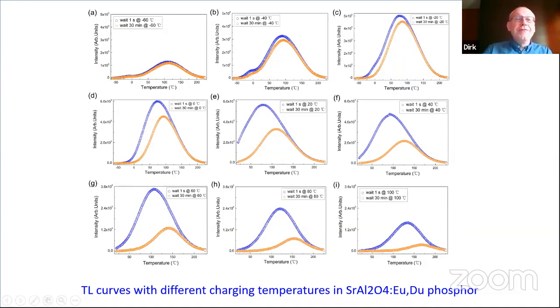On the top left here, we see a thermoluminescence measurement. So we increase the temperature and we look at the light emission when we have charged the phosphor at minus 60 degrees centigrade. Here shown in blue, we have charged the material, so illuminated the material at low temperature, and then we made the thermoluminescence measurements, and we can see that around 100 degrees centigrade light is emitted.